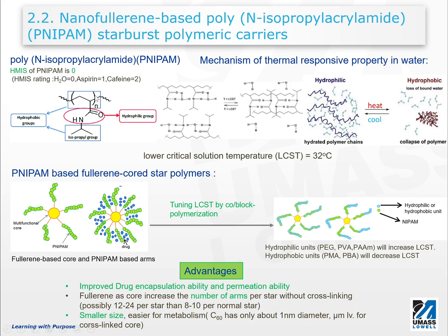If we take a look at the structure here, you can see the amide group in the backbone is hydrophilic, and this isopropyl group is hydrophobic. So the whole structure is amphiphilic. Also, this polymer is somewhat responsive, which has a lower critical solution temperature, LCST, equal to 32 degrees.